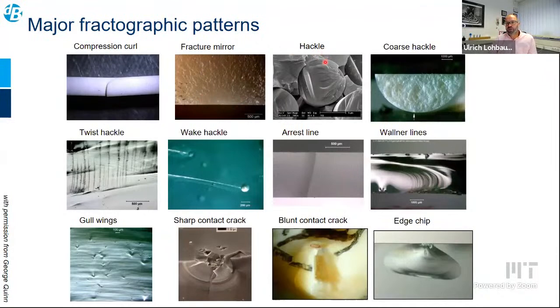Hackle in any type of shape, so a coarse hackle, a twist hackle, a wake hackle developing after a pore when the planes are meeting again. These are very typical fracture features. They guide us towards the fracture origin in this direction. Actually, there are arrest lines when crack velocities change. There are Wallner lines on surfaces, gull wings, contact, edge chips, or some more specific types like Hertzian cone cracks, for example, which is common in dentistry when we are under occlusal loading. So these are very typical types, and we can use them to really trace back the fracture event to the fracture origin.